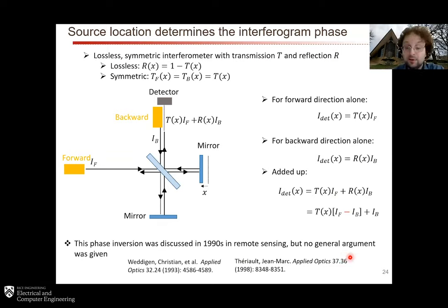in the nanophotonics literature, but it was known going all the way back to the 90s in the remote sensing literature, although there wasn't really a general argument that was given, and we found that a general argument was actually very, very simple. So if you have a forward-emitting source, a Michelson interferometer and a detector over here, an FTIR, and then you also have a backward-emitting source, which in our case were our apertures and filters and so forth, and you make some very, very simple assumptions, for example,